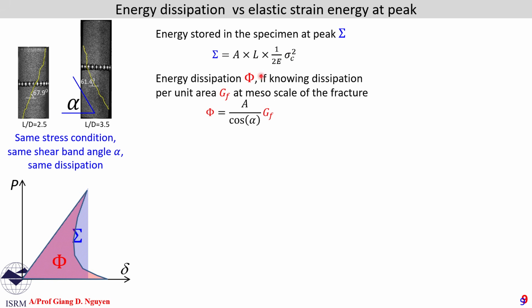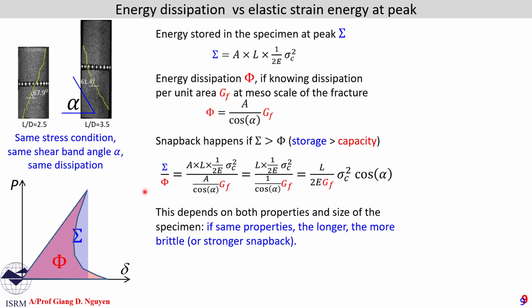The dissipation in this case scales with the area. So given the shear band angle and the cross-section area, we can work out the area of the fracture or shear band. Assuming the dissipation per unit area is GF, we have the dissipation of the specimen at the end of the failure process. So snapback, or class 2 behavior, happens if the storage is larger than the capacity of the specimen to consume energy. As you can see here, snapback happens if the red area is smaller than the hatched blue area.